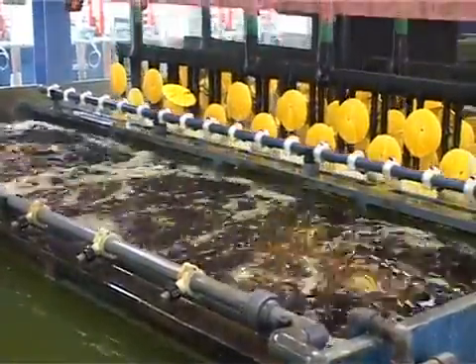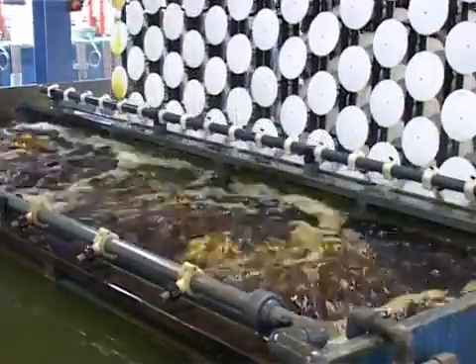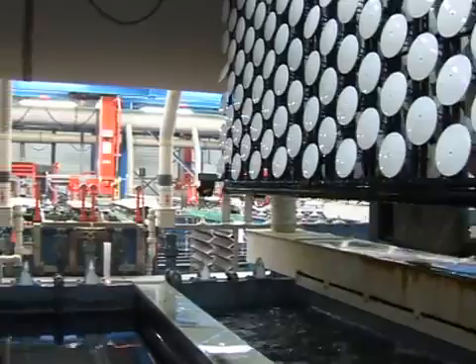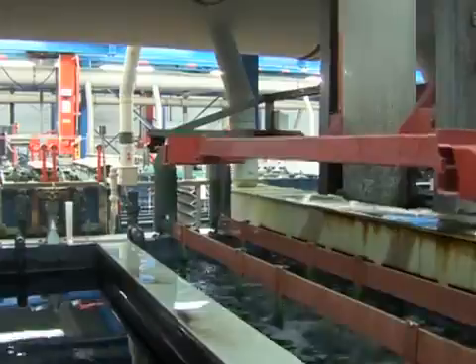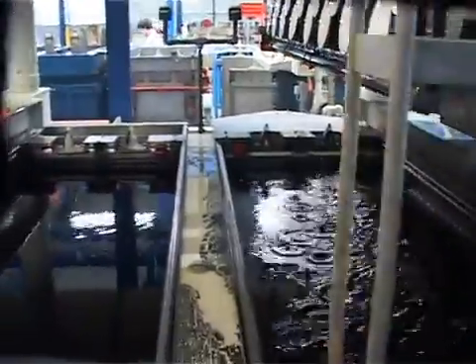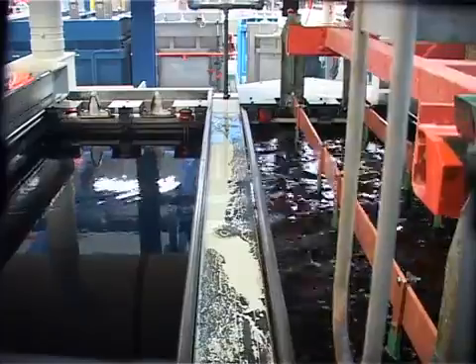After etching, parts are thoroughly rinsed with water, then neutralized in a chemical step that reduces hexavalent chromium to trivalent chromium, since traces of the former will poison the catalytic process. Catalyzing the plastic with the controlled adsorption of palladium and tin colloidal particles in the micropores is critical for making the surface conductive. The next process is referred to as accelerating the surface, where a chemical reaction takes place to oxidize tin plus 2 ions to tin plus 4, and palladium ions are deposited on the surface as metallic palladium.